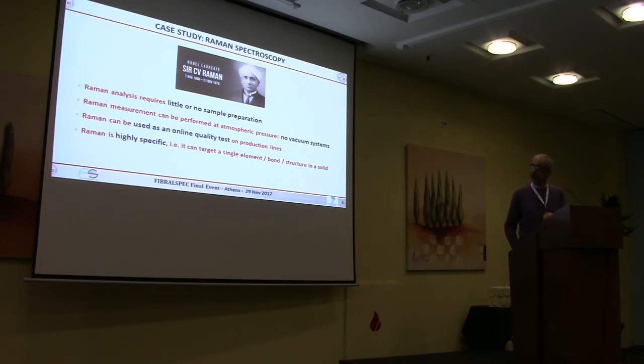So here I'm trying to detail how to approach the problem of Raman in carbon materials. The advantages of Raman are quite well known, because it requires little or no sample preparation. It's a non-destructive technique. You don't need any kind of vacuum system or specific system other than having your clean room. Clean means with no powder, it doesn't mean a clean room in the technical sense. In principle, it can be used as an online quality test, and it is highly specific. It can target specific elements, bonds, or structures in a solid. So these are the advantages of Raman, which we have been working on for a number of years.